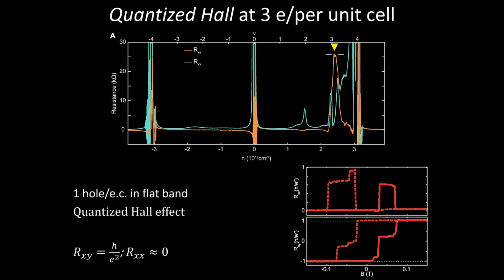If you look at resistivity here as a function of charge carrier density, so we have this twisted bilayer graphene, and we're tuning the charge carrier density. On the top axis is the number of electrons per superlattice unit cell. Okay, so if we go to 3 electrons per unit cell, what I want you to notice is that this orange curve, which is the Hall resistance, gets very large, and the blue curve, which is the longitudinal resistance, goes nearly to 0. Okay, and if you do a careful measurement right at 3 electrons per unit cell of the Hall resistance or the longitudinal resistance as a function of magnetic field, you find that indeed it's magnetic, but moreover, that Hall resistance is quantized, and the longitudinal resistance vanishes just like in the integer quantum Hall effect.